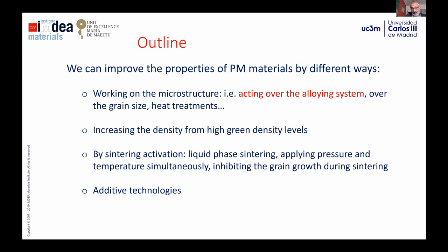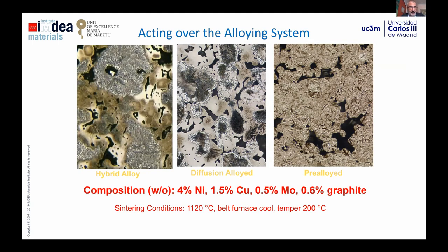So regarding the first of the topics, we can act over the alloying system. Just to show you one example. Here we have a conventional PM steel with nickel, copper, moly, and graphite, and with some specific conditions: 1120 degrees, furnace cooling, and then tempering. You see that we can have three completely different microstructures, and depending on the microstructure we will have different properties. These microstructures can be obtained depending on the way in which we treat the original powders: hybrid alloys, diffusion alloying powders, or fully pre-alloyed powders.